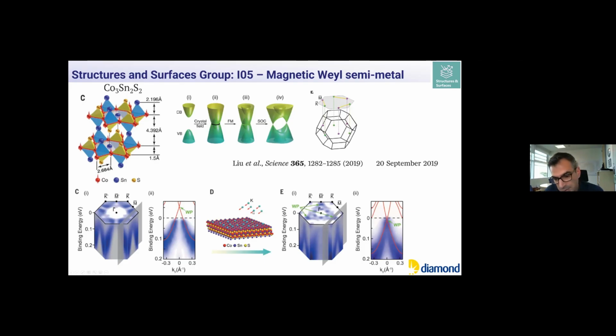But by doping the system, you can actually push down this Weyl point, this crossing point, below the Fermi level. And so there's a lot of activity, not only studying this material, but trying to dope them in situ without leaving the beamline, and then recollecting data to see how the effect of such doping or chemical modification can affect the properties of the system.